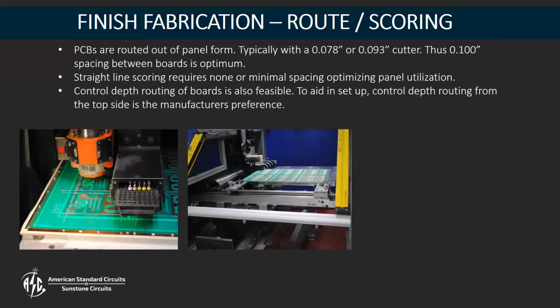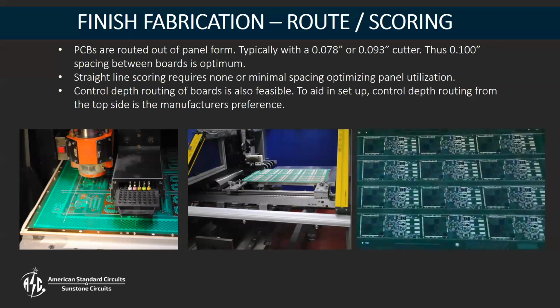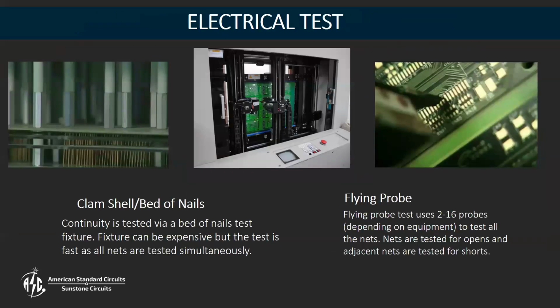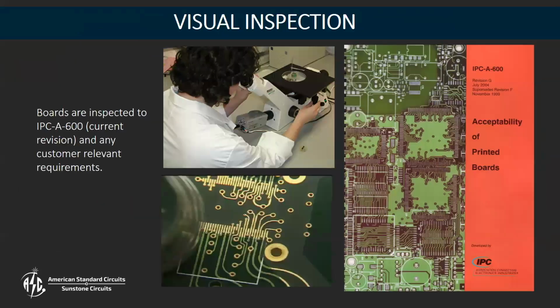All right, once that surface finish is done, we're basically able to singulate out our boards, whether that be into an array or into a single image. So we add any non-plated holes, route any cutouts or slots at this point that are non-plated, and then singulate the boards into their correct array. There's one, for example. Electrical test, boards get tested. You know, a lot of volume orders get done through clamshell or bed of nails. Sunstone, we don't use that anymore. We got rid of that process a number of years ago, and everything goes through a flying probe process where we're checking for continuity and isolation.